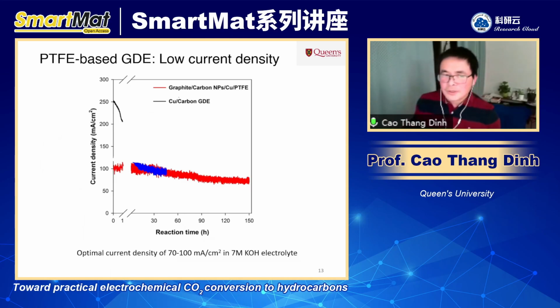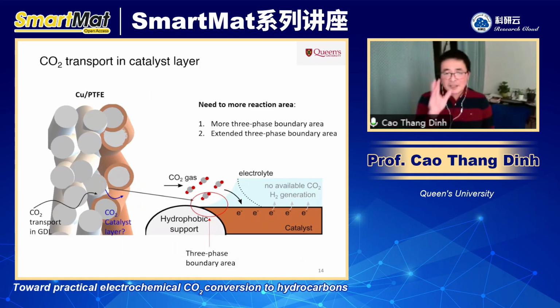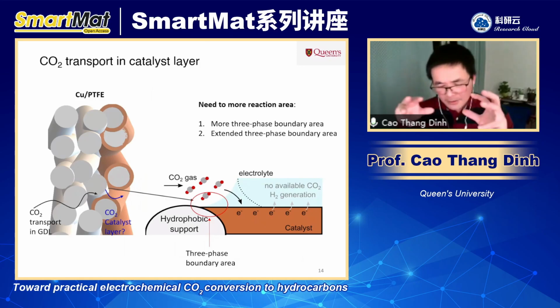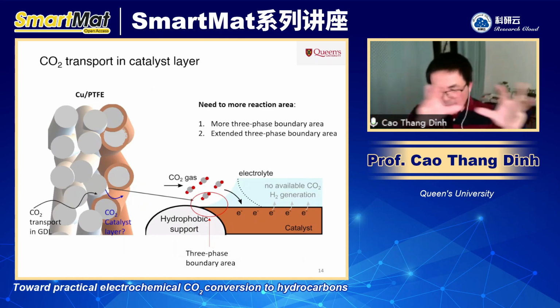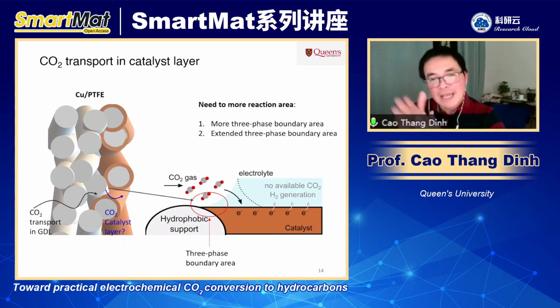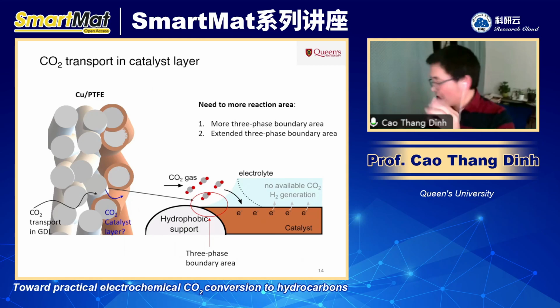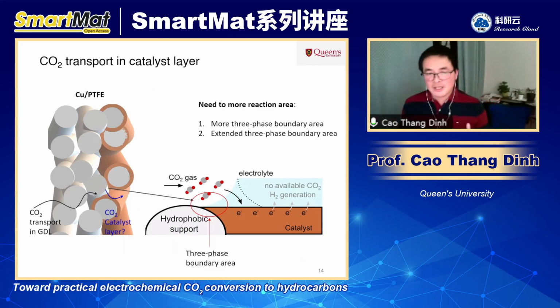And that leads us to the second thing here. What is the role of the gas diffusion layer? With the gas diffusion layer, we bring the CO2 from the gas phase to the interface between gas and liquid, right? That is where the catalyst is located. If you look at the figure on the left-hand side, the PTFE layer, the white layer here, the CO2 can penetrate through that, no problem. But then you see that orange layer here, that is the catalyst layer. And in CO2 conversion, the catalyst layer is often hydrophilic and filled with water, right? So you can bring the CO2 to the interface, but you cannot bring the CO2 everywhere.